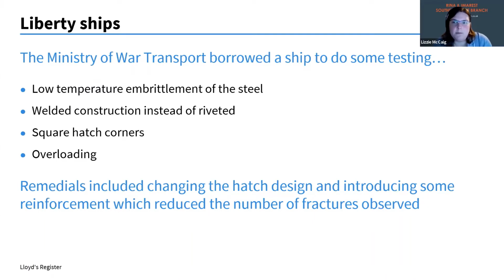One thing they found was that because the ships were sailing in the North Atlantic in winter, they were being exposed to temperatures that could fall below the critical point where the steel changed from being ductile to becoming brittle. So that allowed cracks to start easily. Because they were using welded construction, that allowed the cracks to propagate from plate to plate, whereas in a riveted plate, you get to the edge of the plate and there's nowhere for the crack to go. They get arrested when they hit that edge of the plate.